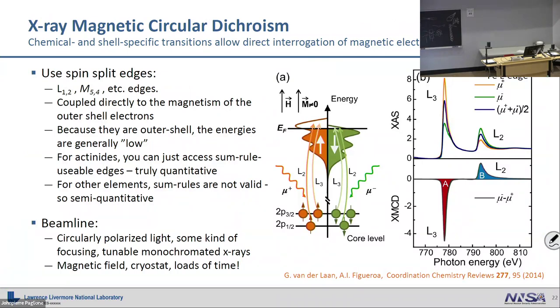And while neutrons are great at that, X-rays really don't couple to magnetism very well at all. There are some resonant magnetic diffraction techniques you can use, but this is probably the biggest workhorse that people use for this. And so the idea behind this one, this is an example of what you would get in iron. There's tons of XMCD data on iron in the literature.